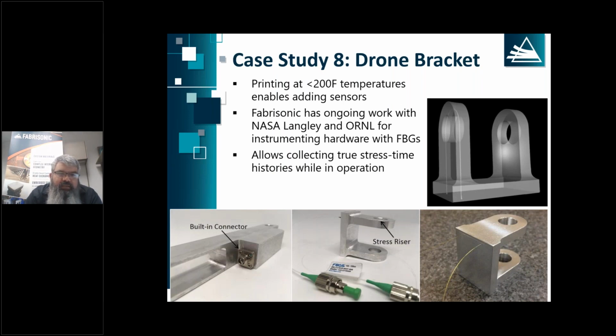They were looking at a drone and trying to correlate flight data with actual computer models. So here again, we embedded fiber optic strain gauges into a bracket for a drone. And we were able to collect true strain time histories as that part was loaded in the field. And that data was fed back into the development of the model so that we could get actual true strain time histories as the part was being used.